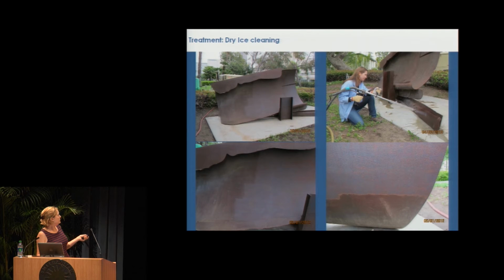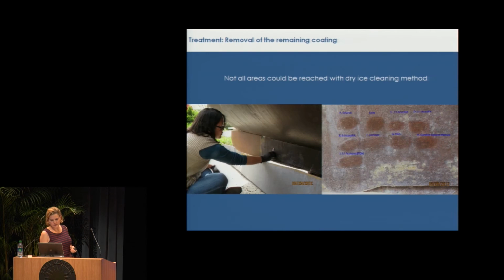And here you see the before and the after. You see that we blasted through a lot of the corrosion layer, because some areas were easier to go through than others, and you often get to the bare metal, but we didn't really have an option, because cleaning the corrosion layer with solvents would have needed a lot of solvents. And this was, in the end, a clean technique, and we could take all the coating off. So I was very happy about that.